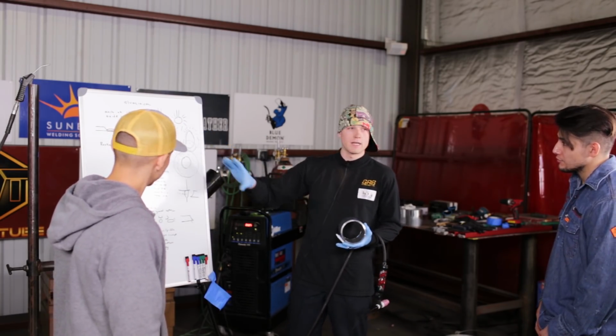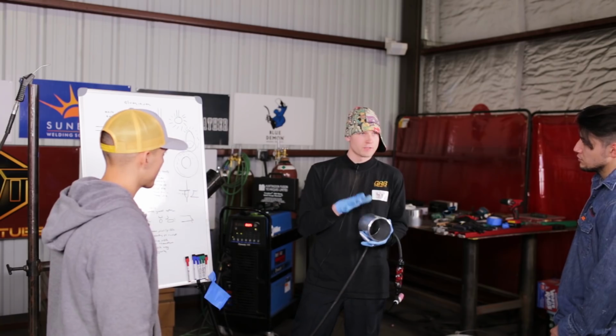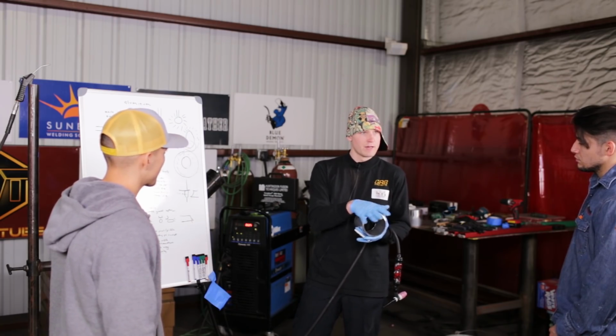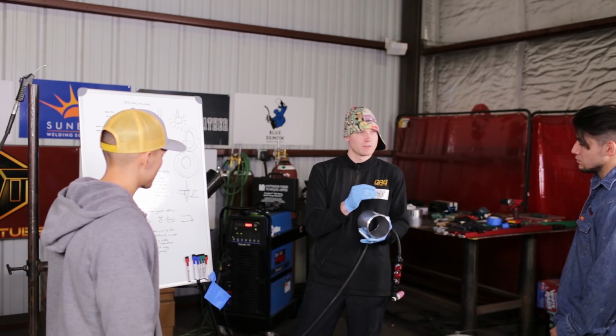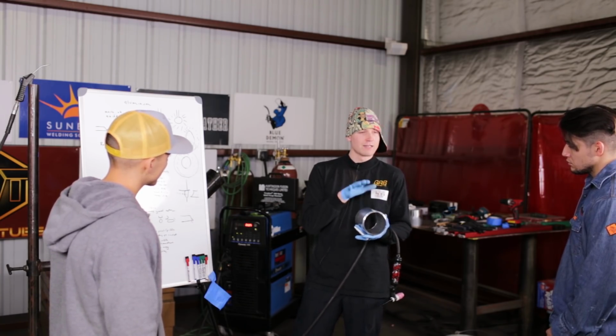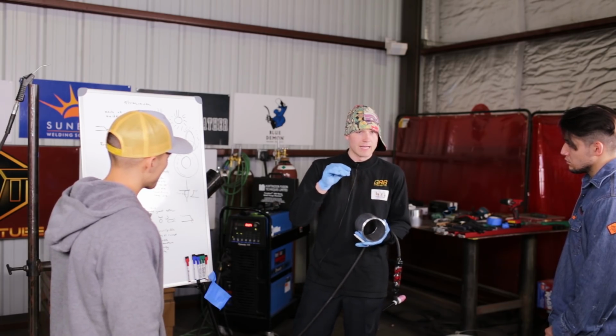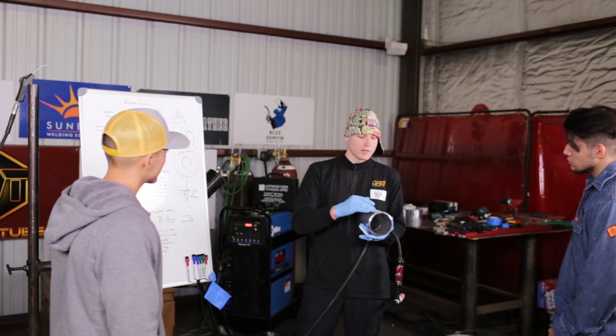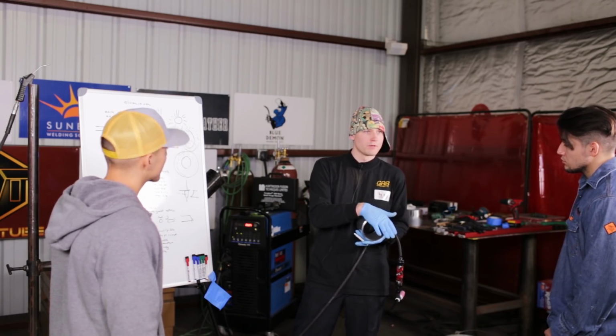And also the purge quality and the formation of oxides from the titanium weld, in parts per million, also equate to aluminum, because as you heat up aluminum, it rapidly forms oxides. With fewer parts per million of oxygen in the atmosphere on aluminum, you get a lesser thickness of oxides, in nanometers, that you're going to form. But the other thing with aluminum is that it does not form heat tint like stainless steel, in the sense that it's not going to have light straw, yellow, blues, purples. It's going to be silver. It's a shiny version of titanium, and you do not weld over the shiny silver.